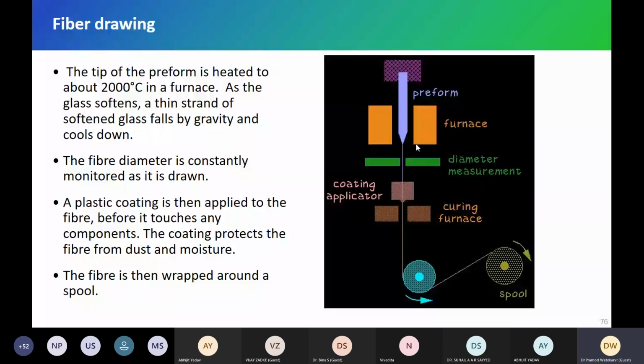We pull it down, and there are wheels here, which are continuously rotating. So we put the fiber here, and as the wheels rotate, they start to pull it continuously. The preform is heating continuously, the fiber is coming down, and afterwards it is pulled automatically. Initially it is manual. We put that fiber here, and then because of these rotations, it continues pulling the fiber.